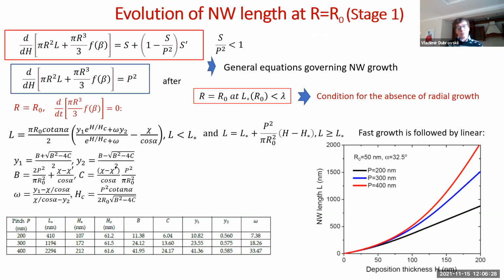So that's the reason. Now, if we have no radial growth at all, we can describe fully analytically the evolution of nanowire lengths in such a growth on a reflective substrate. This is basically the governing expression for the total volume. But if the radius is fixed, I can immediately get the solution, which is quite interesting because it's not exponential. It contains an exponential term, but it's more complex than exponential compared to what we have modeled before for MBE-grown nanowires